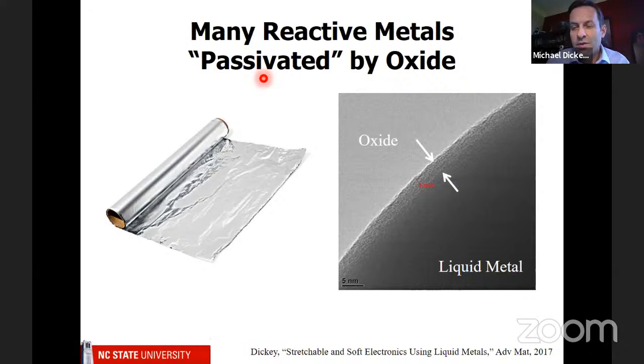They would just react with air, other than gold and platinum. And so what do we know about this oxide? Well, here is a picture of our liquid metal, and this is a side view. So you can see the oxide is a few nanometers thick. So it's very, very thin.